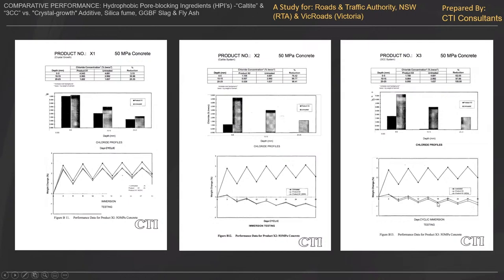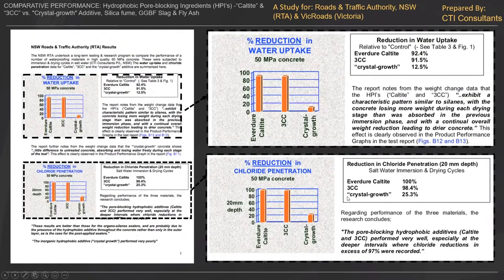But the important thing is that line is going down. Every drying cycle is losing more water than it's reabsorbing at the next phase of the test. So this is a summary. So either your calcite or the HPI, full HPI, 50 MPa concrete, the reduction in water uptake is 92.4%. 3CC, which is the other product that we used at lower doses, 91.5%. Crystal growth products, on the other hand, another type of water product, 12.5%.